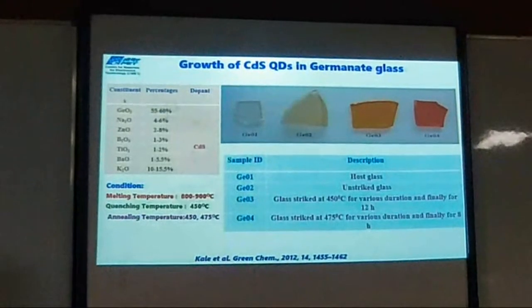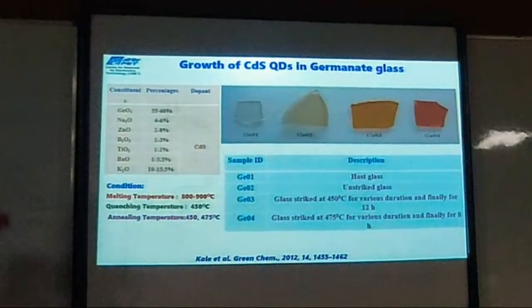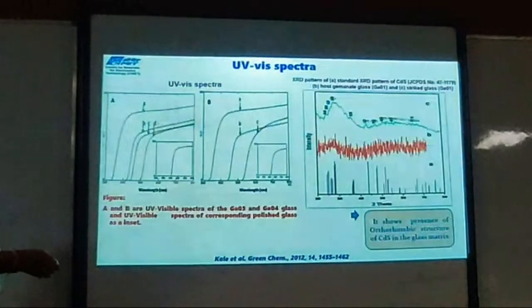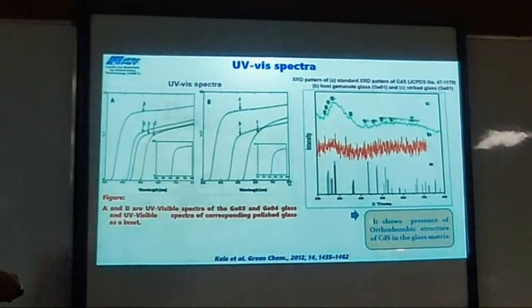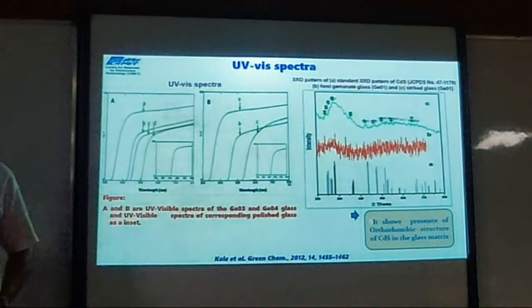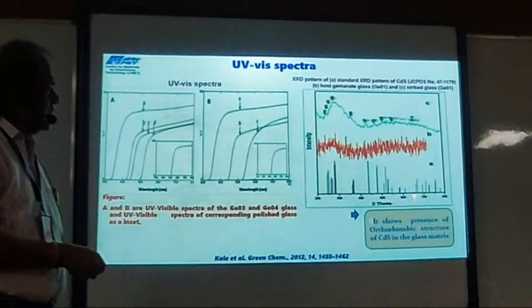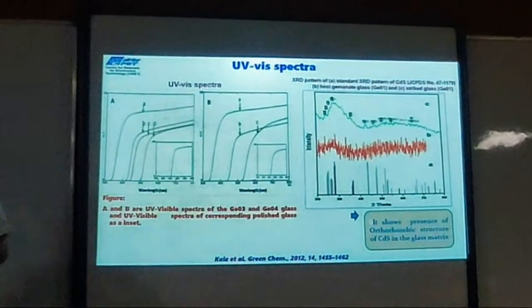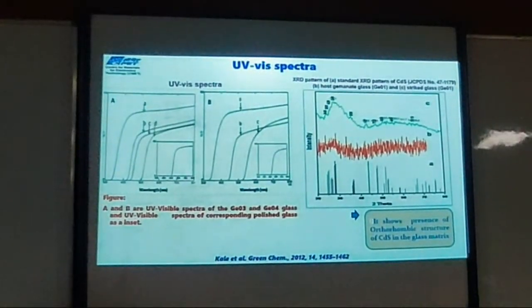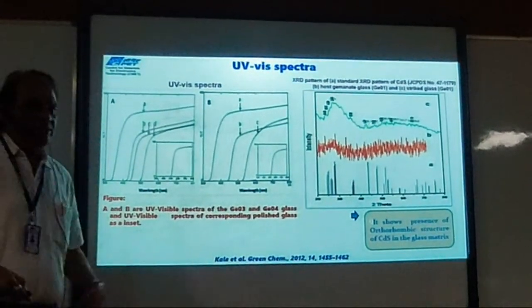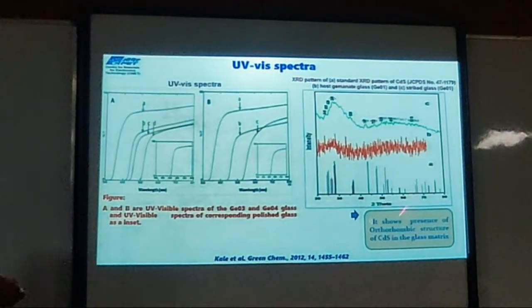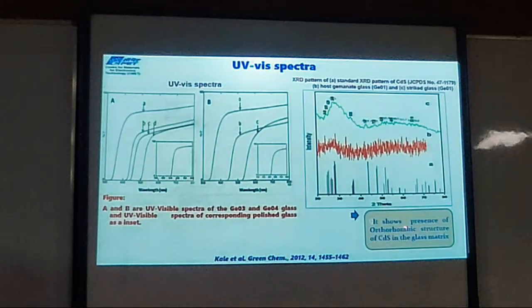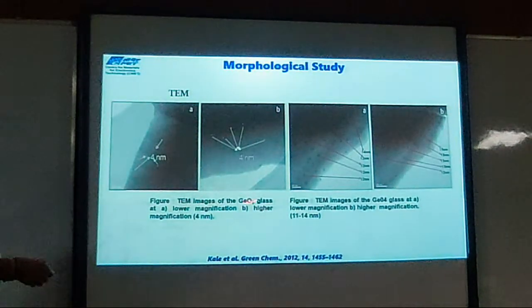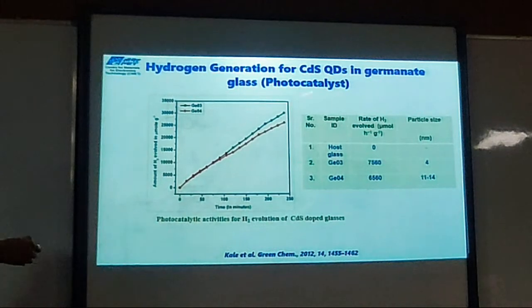Typically the same, but initially with silicate glasses, I thought whether we can have low temperature glasses, which give much more effect. Incidentally, what happened is that the cadmium sulfide which you dope, here we are getting orthorhombic cadmium sulfide, which is a metastable state, but this metastable state is stable in the glass. So that was a new invention, and this metastable CdS is much more visibly active as compared to other cadmium sulfide.